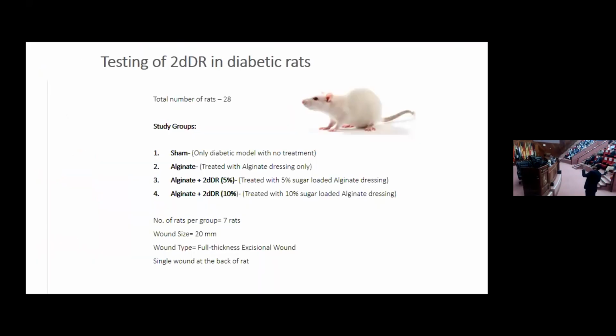So back to the in vivo assessment. We were really interested in seeing whether this technology will be effective for diabetic wounds. They're relatively difficult to heal when the patients have diabetes. We took alginate dressings. These are very, very standard dressings, which are used worldwide for healing wounds. We took two concentrations, 5% and 10% weight percent of the sugar, and tested this on the rat.